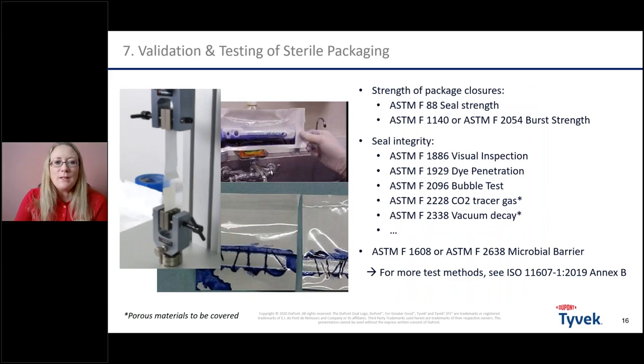So in terms of validation and testing, I just listed a few typical test methods which are used a lot with porous packaging, with Tyvek packaging, for instance, but also other packaging. In terms of strength, you need to, of course, demonstrate that your seal strength can withstand handling, sterilization, transport, etc. So you can test ASTM F88, which is also the picture on the left side with the tensile strength equipment, which is very punctual and very good because you can examine and judge all the different seals. Or some also use burst strength testing, an overall strength test to see how much pressure the packaging can withstand.